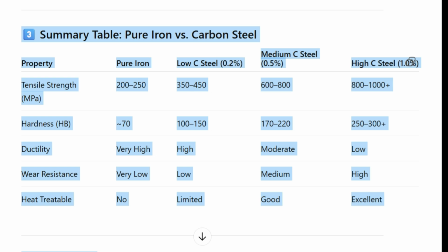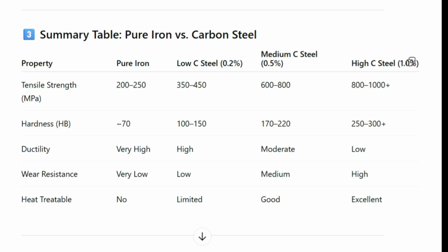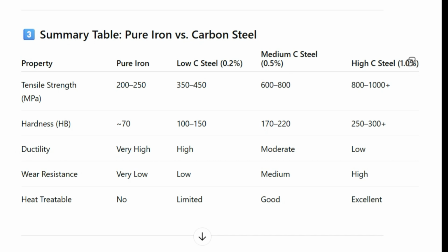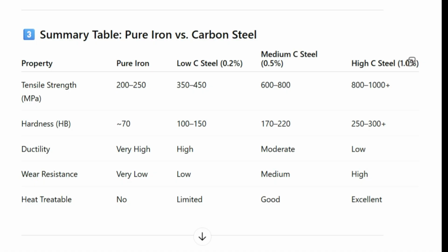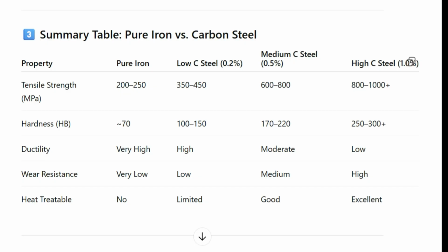Look at this table. Tensile strength: pure iron has very low strength, 200 to 250 MPa. Low carbon steel, still with 0.2% carbon, has a tensile strength of 350 to 450 MPa. So you can see up to 0.2% carbon is giving so much strength. Pure iron almost does not contain carbon, 0.0005 or something like that, a very negligible percentage. Now, when you increase the percentage to 0.5, it goes to 600 to 800 megapascals. So more carbon is giving such huge strength.